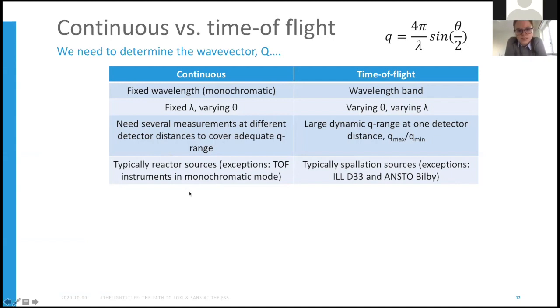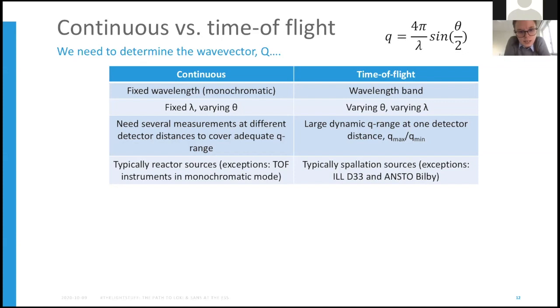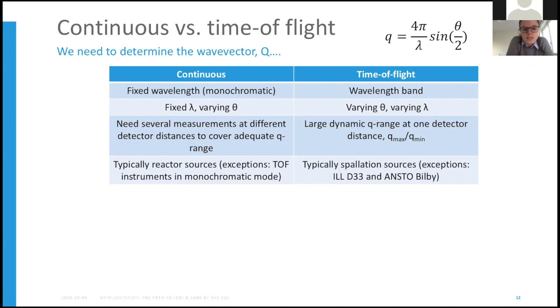The other way of measuring SANS is time-of-flight. In this scenario we use a wavelength band instead of a monochromatic beam — say 2 to 10 Ångströms rather than a single 5 Ångström beam. It's called time-of-flight because the time it takes a neutron to travel from source to detector is directly proportional to its wavelength. Using this method we can access a large dynamic q range at just one detector distance. These experiments are typically performed at spallation sources.